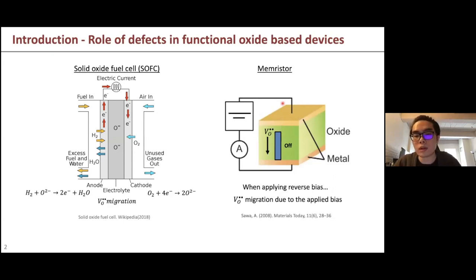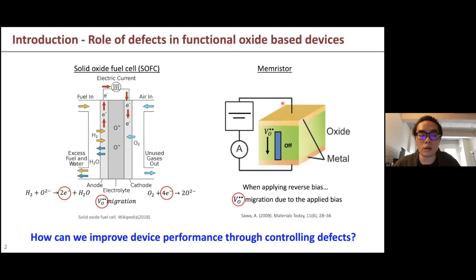And when you apply a negative bias, the oxygen vacancies move toward the other direction. So it breaks the bridge and makes the conductivity of the whole thing lower. So you can see this as a zero state. In both cases, the oxygen vacancy plays a very important role in the operating principle.